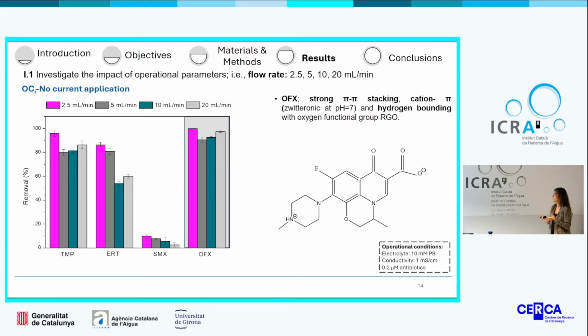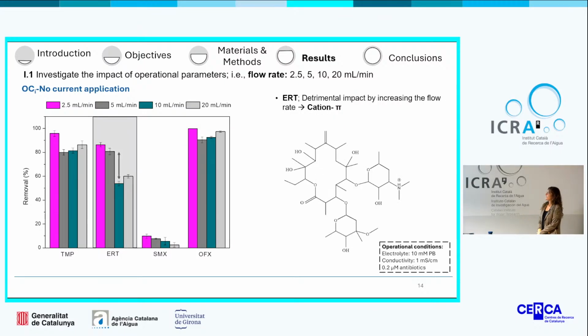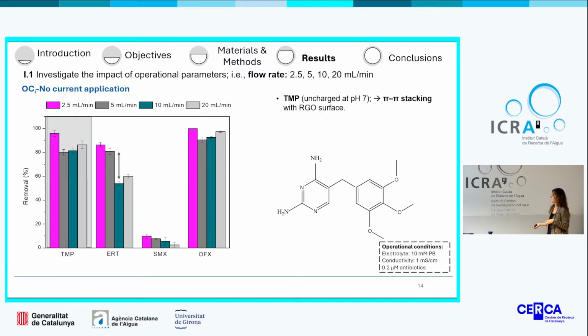On the contrary, ofloxacin is governed by several interactions, for example, strong pi-pi interactions between the molecule and the different aromatic rings of the reduced graphene oxide, cation-pi interactions, since it's present at neutral pH as a zwitterionic molecule, and also different hydrogen bondings between the zwitterionic molecule and the different oxygen groups of the RGO. In case of erythromycin, as we can see, it was a little bit more affected by the increase of the flow rate. This is probably a consequence of the weaker cation-pi interaction with the positively charged antibiotic. In case of trimethoprim, quite similar to ofloxacin, it was almost completely adsorbed in all studied flow rates.